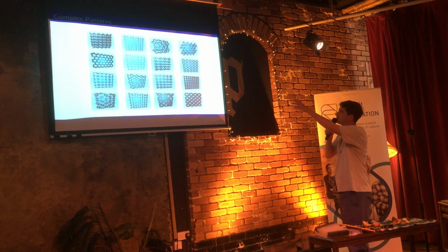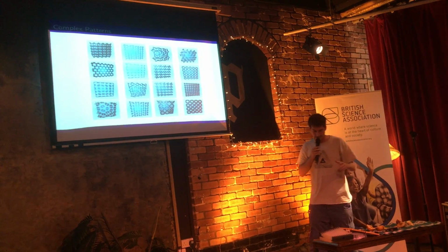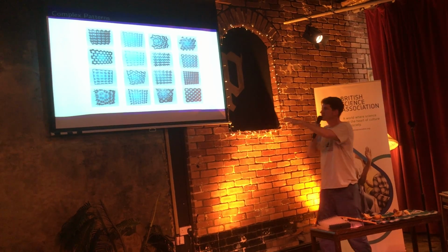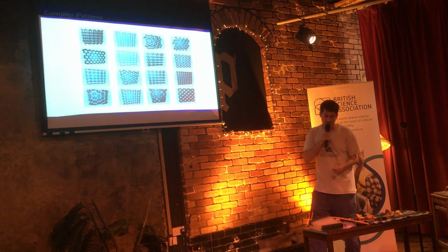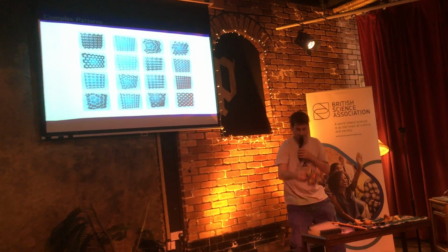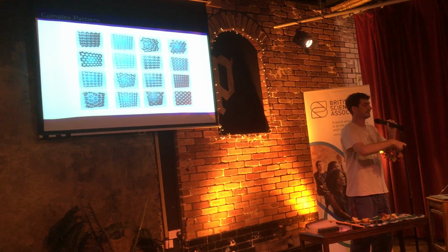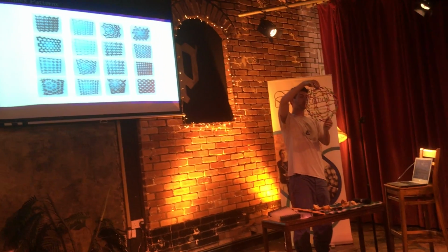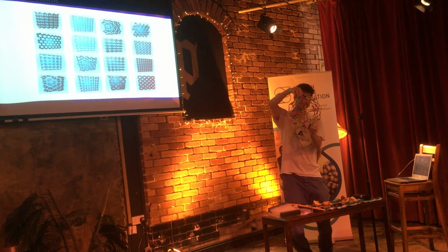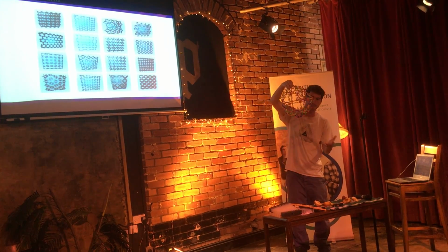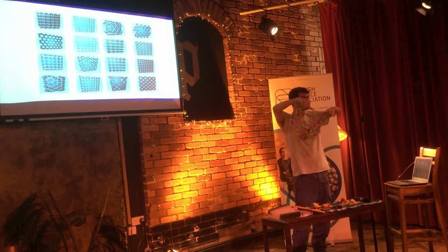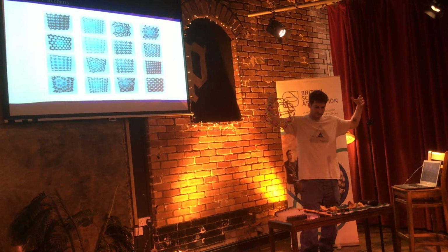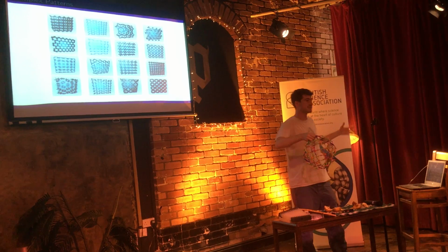So these are a few that are kind of special because most structures, when you pull them in one way, they get thinner. Whereas these structures have a negative Poisson ratio, which means that, like this structure, when I expand it, you'll find that it just expands in all directions. And this is really interesting because if you get an impact on something, or it gets pulled, the cells can work together in this cool way where they can just help deflect the force into somewhere else.